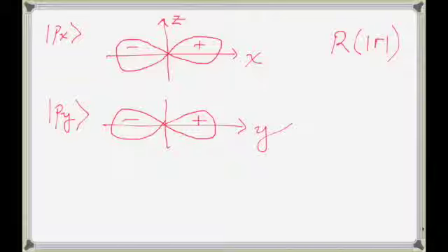So we have to understand this to get the sign of the matrix elements correct. The magnitude is just determined empirically to give you the best fit to the known band structure, effective masses, and gaps. But we need to understand this to get the sign of our matrix elements correct, and that is critical.